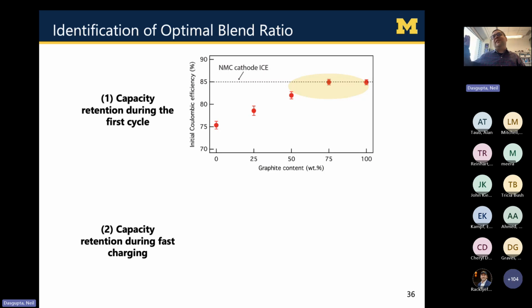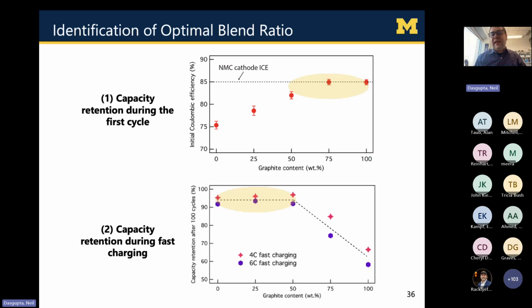This is a well-known limitation of NMC cathode materials and batteries, that they lose their reversible accessible capacity due to these structural changes in the first charge cycle. What that means, however, is that if I blend in, notice I go from 0% to 25 to 50, if I blend more and more graphite into the hard carbon, eventually I see that above about 50%, you don't even notice that the hard carbon is in there anymore because you're still limited in your first charge Coulombic efficiency by the presence of the cathode material.